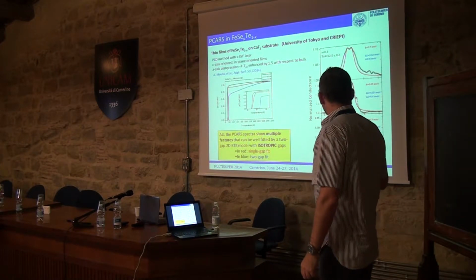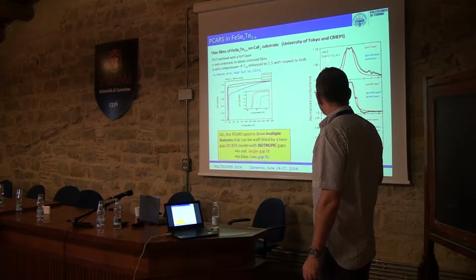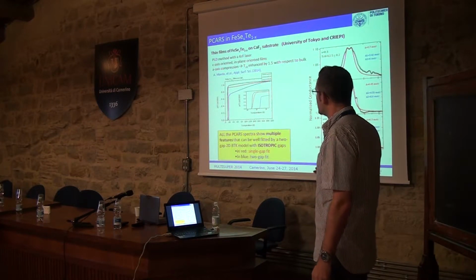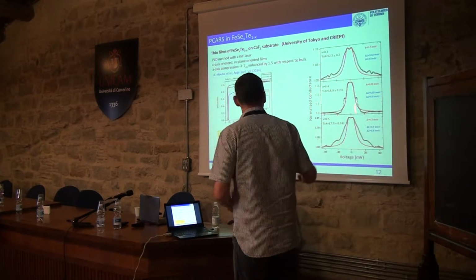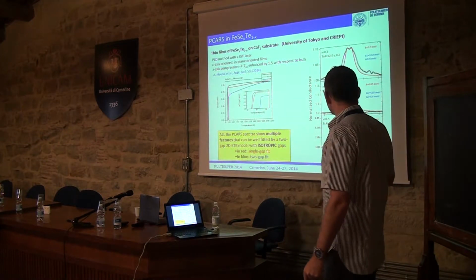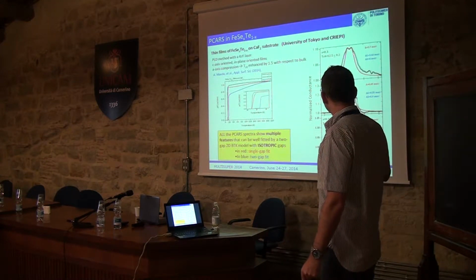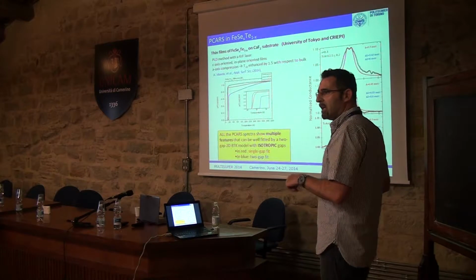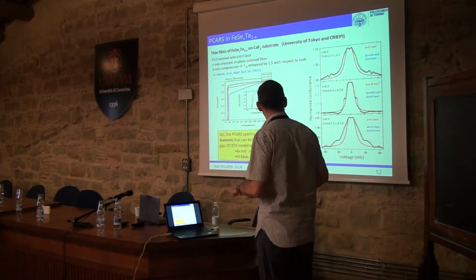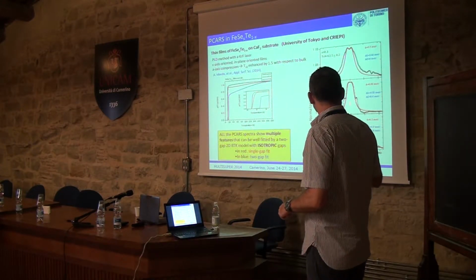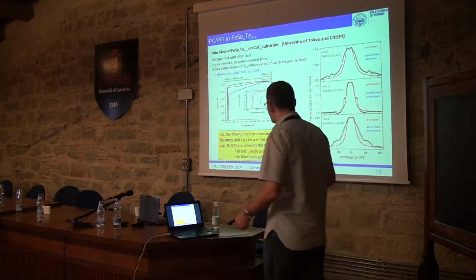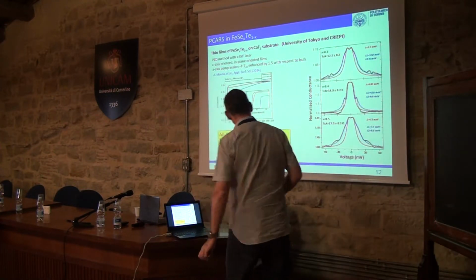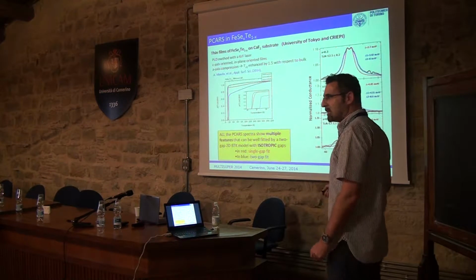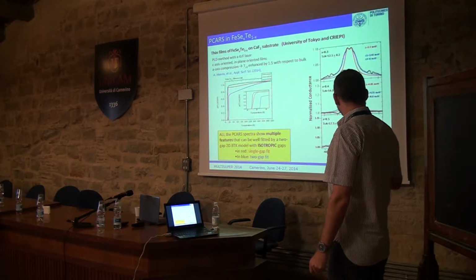These are three examples of spectra taken at 30%, 40%, and 50% selenium content. All the spectra show multiple features, so that if you fit the spectra by using a single gap, single band BTK model, you completely lose a big part of the curves. Then it is possible to fit them by using a two-band BTK model, and the fit is almost perfect.